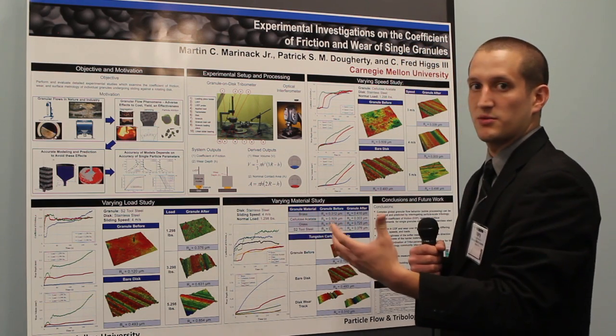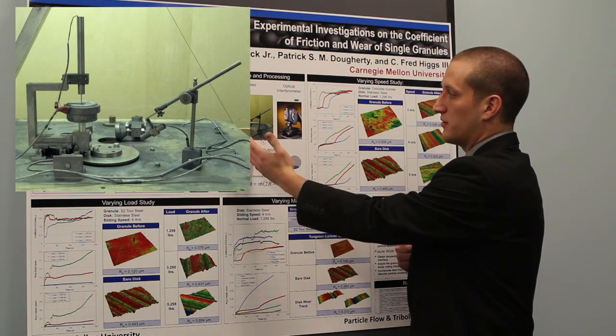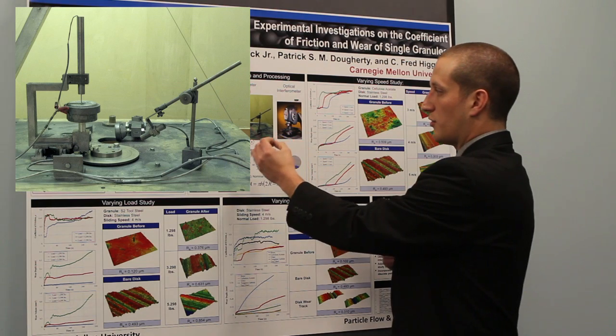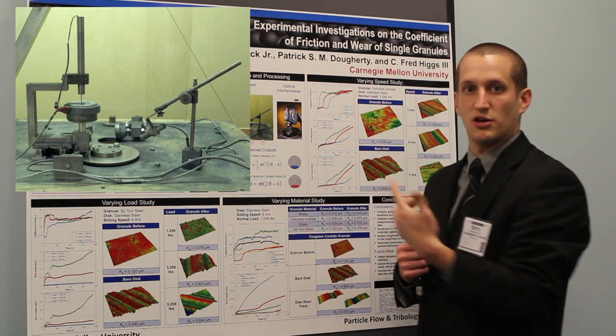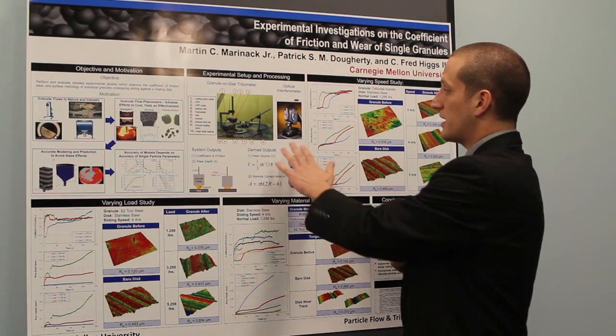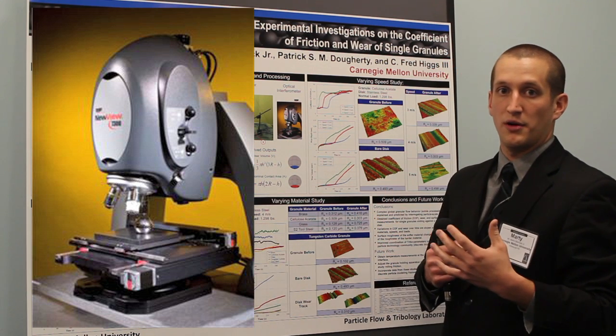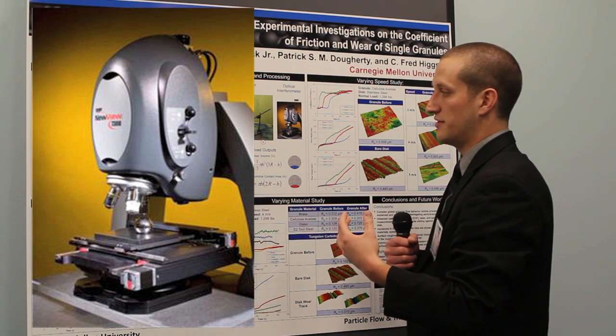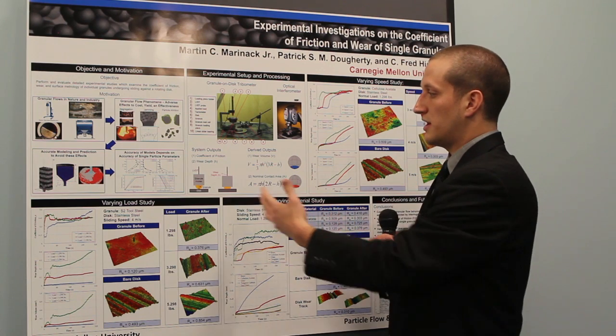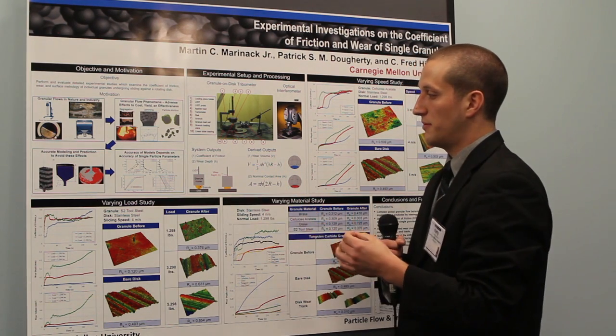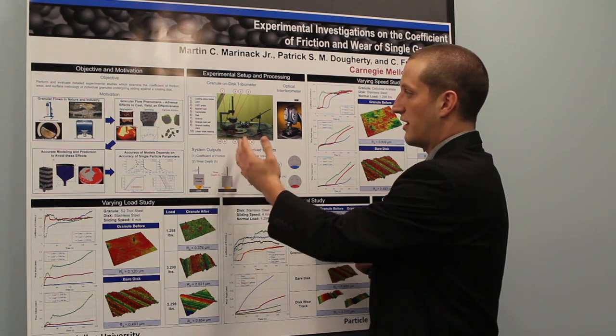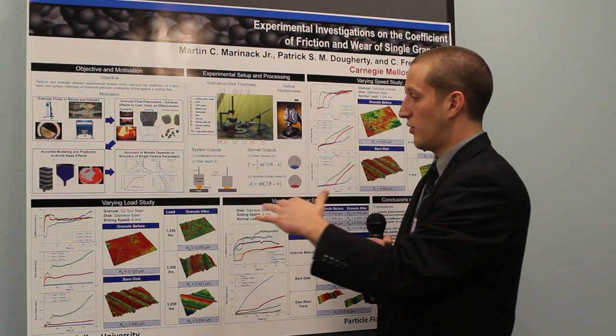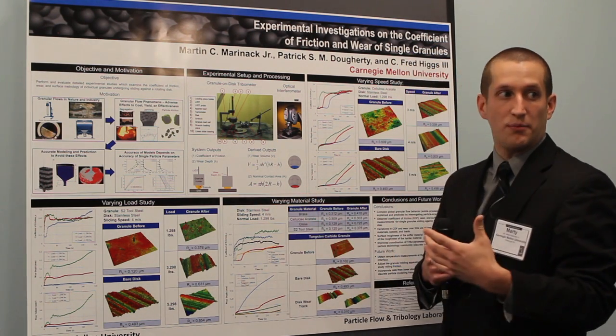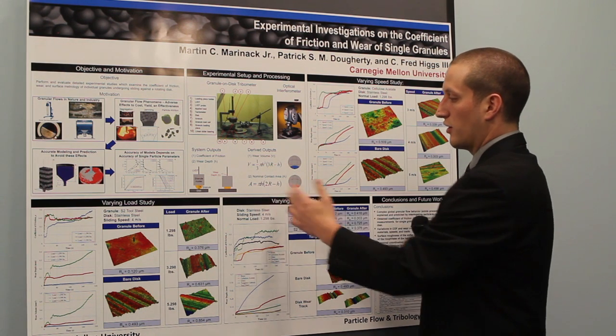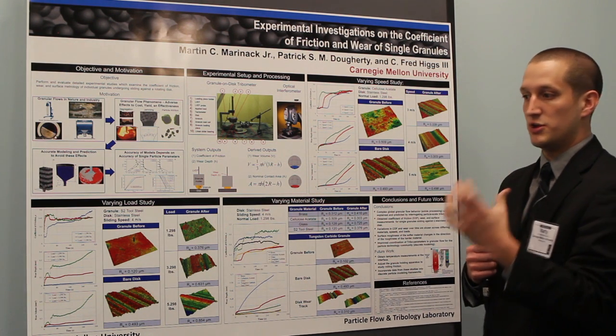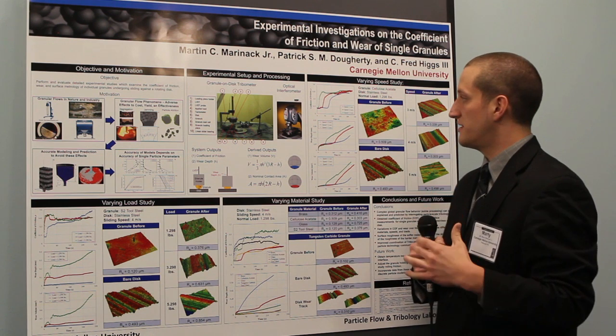So the way we conduct this research is we use a granule tribometer, which I show here, which simply holds a single granule by means of a holder against a disc, which is going to rotate. And then we also use an optical interferometer to get surface measurements both before and after testing. So from our system, what we get is two measurements. We get coefficient of friction and wear depth, which is simply the length of extension of an LVDT device as the granule wears. And from those two outputs, we can derive two other outputs, which are the wear volume and the nominal contact area between the surface of the granule and the disc.